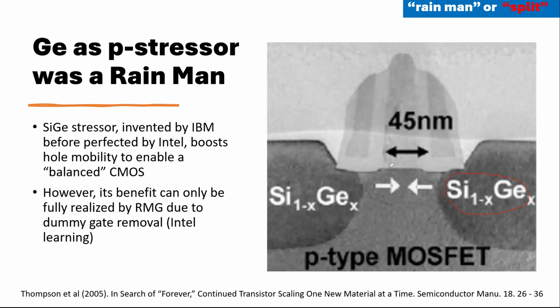When you take the dummy gate out, this becomes zero, becomes free space. That's the time the channel can really be compressed. So they will move in a little bit more, and that really captures the stressor effect. And then you put your high-K metal gate back on, and you maintain the strain state.